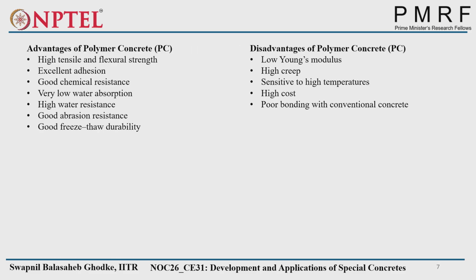So what are the advantages and disadvantages? Advantages: high tensile and flexural strength, because it's a chain reaction, so the tensile strength will be very high. Excellent adhesion, good chemical resistance, very low water absorption, high water resistance, good abrasion resistance, and good freeze-thaw durability. But disadvantages: low Young's modulus, high creep, sensitive to high temperature, high cost, poor bonding with conventional concrete.